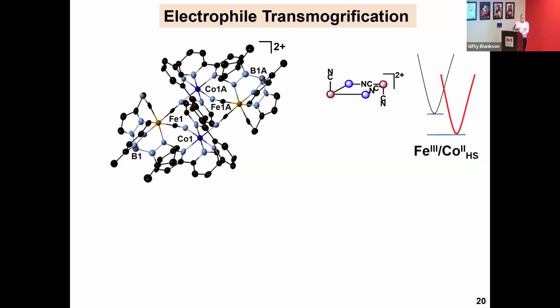So we thought, all right, that's our square. We can think about this in terms of a state diagram where that's a long cobalt nitrogen distance and it's composed of these metal-metal pairs. If we add an electrophile, we attach it to the terminal cyanides. That should remove electron density from the iron and, by induction, the rest of the cluster.